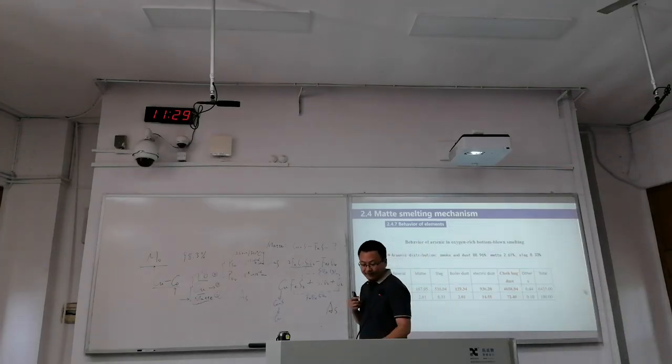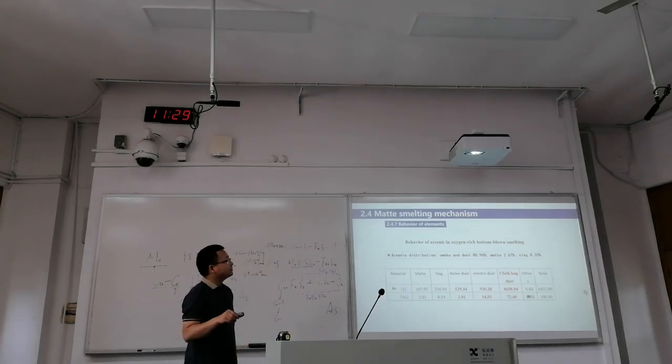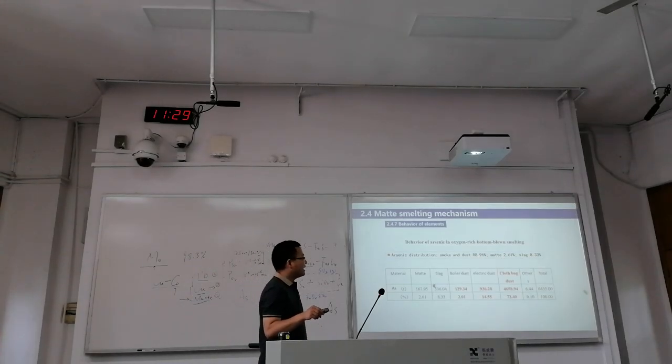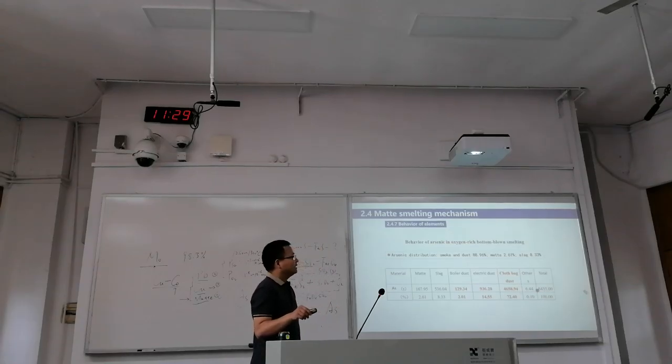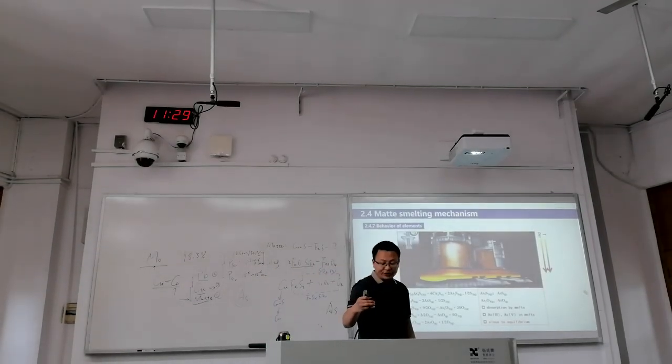And we have some summaries below. So this is arsenic distribution for the dust, like 90%. For the slag and the metal, only 10%. And if we are having these values, the total in the system will be like 6,000 tons. 6,000 tons. And let's try to talk about the reasons.